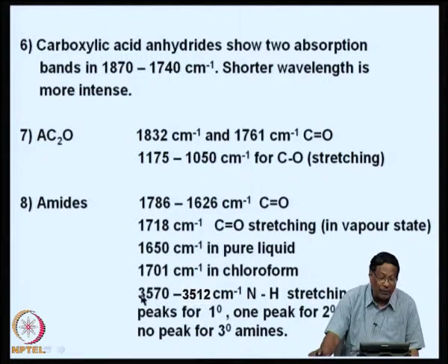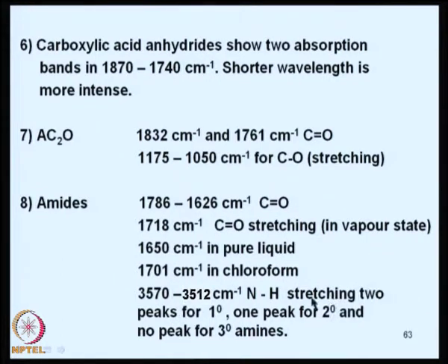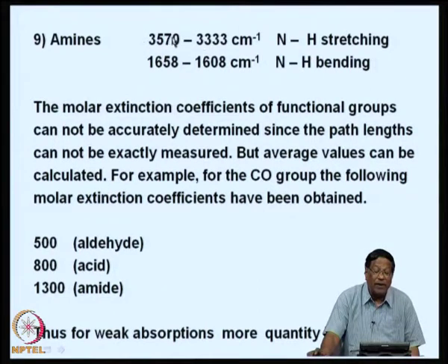lines, that is 3512 centimeters inverse showing NH stretching. It shows 2 peaks for primary and 1 peak for secondary and no peak for tertiary amides. That means, if you suspect it to be an amide, by looking at the number of peaks in this range, you will be able to decide whether it is primary, secondary or tertiary. So, that is very interesting. For example, amines also show, if it is a primary or secondary amine, that 3570 to 3333 centimeters inverse is where the NH stretching frequency occurs, and the NH bending frequencies, being lower in energy, would appear at 1658 to 1608 centimeters inverse because they require less energy.